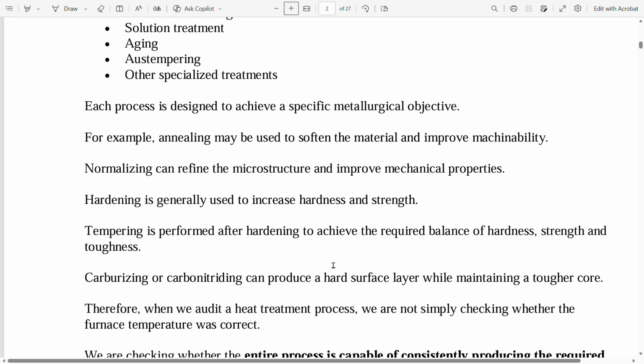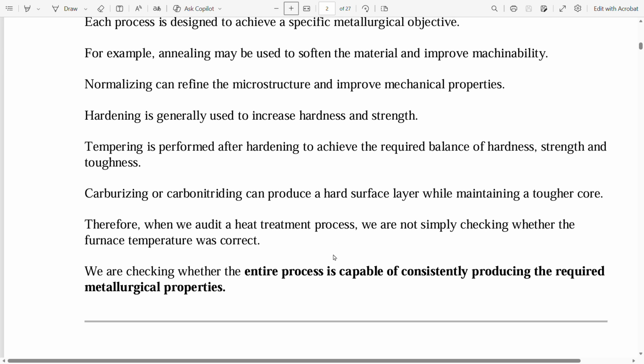For example, annealing may be used to soften the material and improve machinability. Normalizing can refine the microstructure and improve mechanical properties. Hardening is generally used to increase hardness and strength. Tempering is performed after hardening to achieve the required balance of hardness, strength, and toughness. Carburizing or carbonitriding can produce a hard surface layer while maintaining a tougher core. Therefore, when we audit a heat treatment process, we are not simply checking whether the furnace temperature was correct. We are checking whether the entire process is capable of consistently producing the required metallurgical properties.